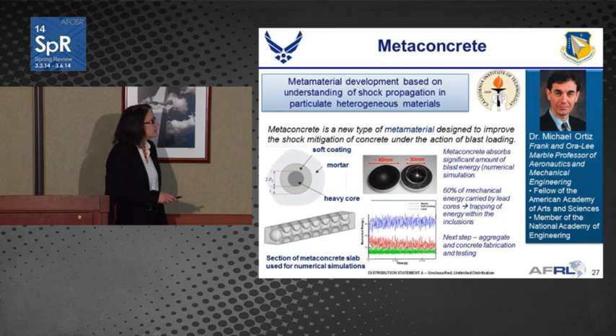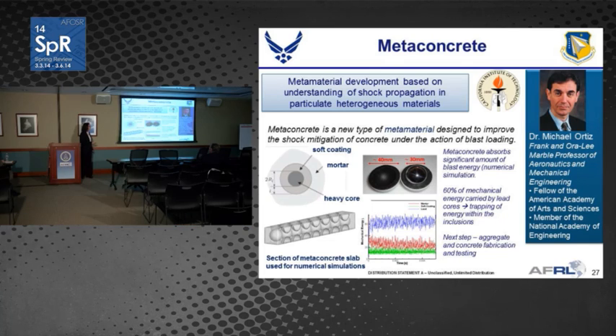And here you can see experimentally what they're looking at: as they propagate a shock through this material, they're actually capturing the mechanical energy in the vibrating lead cores, and it's mitigating the shock wave as it propagates through the material. So they've been able to determine this computationally, and the next step is to actually build these materials, the aggregates and the concrete, and ultimately test them to see if their predictions are true.